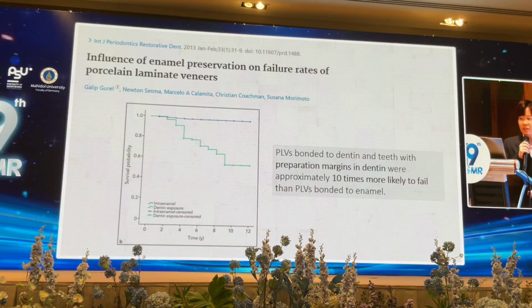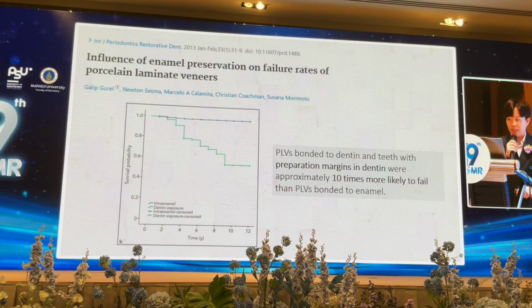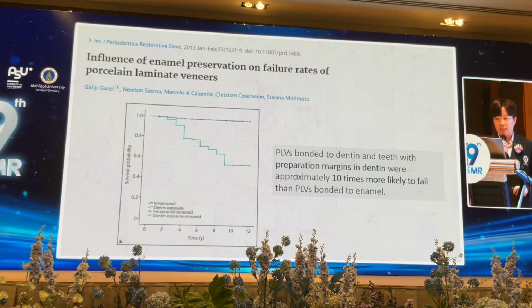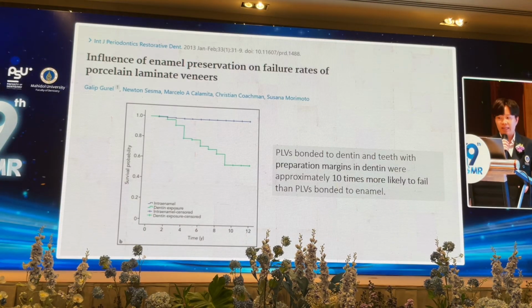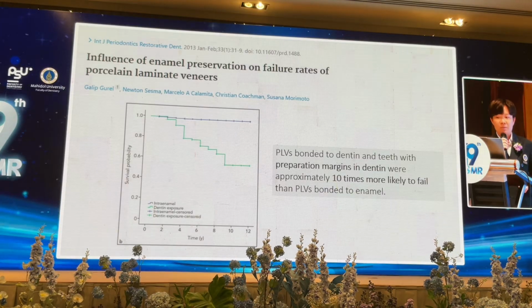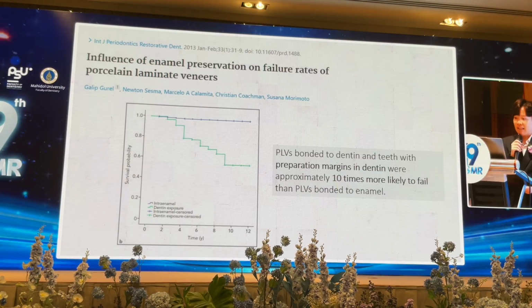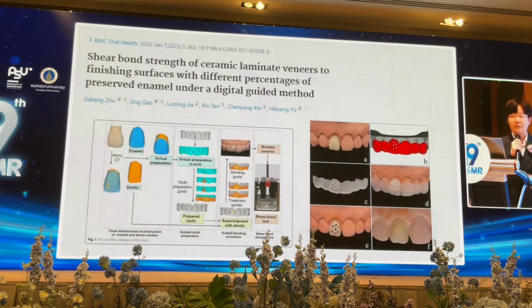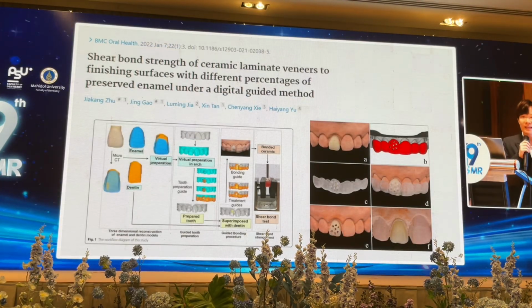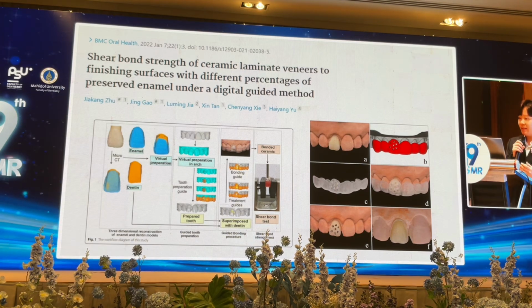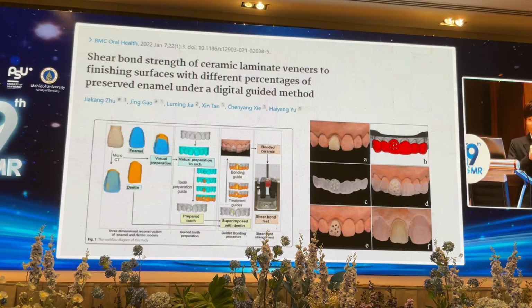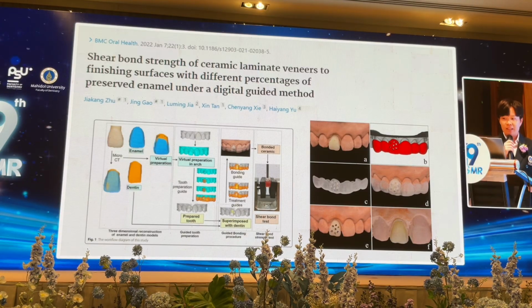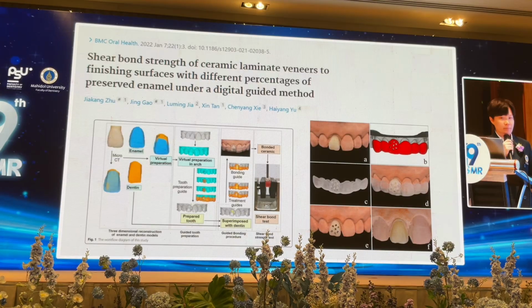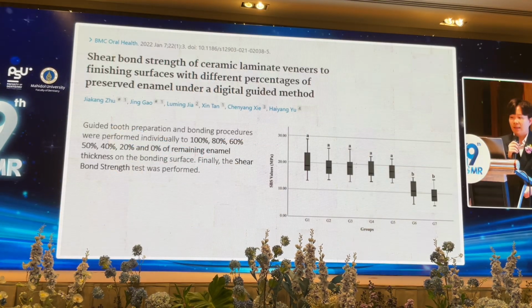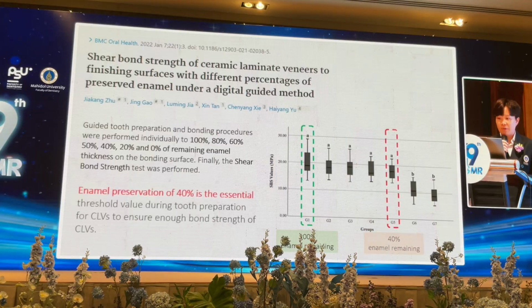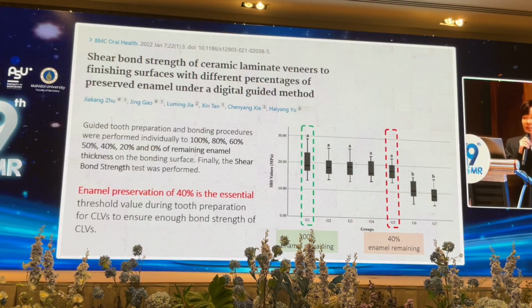And research shows that ceramic veneers bonded to dentine, or with margin placement in dentine, are about 10 times more likely to fail when compared to those bonded totally to enamel. This clearly highlights the importance of preserving enamel for the preparation margin. So, the question is, how much enamel do we really need for an ideal bond? Research tested veneer preparation with varying percentages of remaining enamel, guided by the digital design. And the findings indicate that leaving over 40% of enamel is enough to achieve a bond strength similar to that